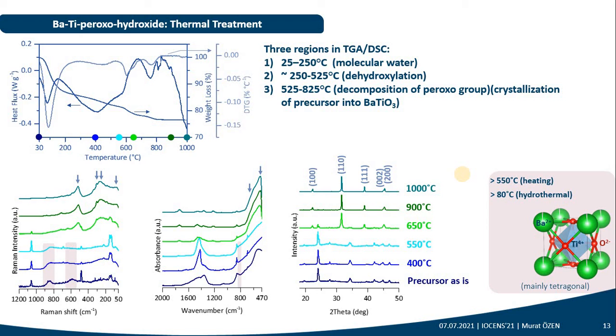The present work shows that the titanate precursor material synthesized by the peroxo route is actually a very high quality precursor material to synthesize crystalline barium titanate, and depending on the synthesis method, for example, when we use thermal treatment, the precursor material will be transformed to barium titanate at above 550 degrees Celsius. When we use a wet chemical method such as the hydrothermal method, the material will be transformed to barium titanate at even lower temperatures, for example 80 degrees Celsius and higher.